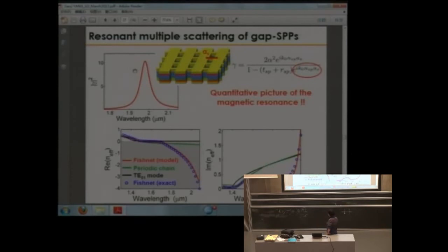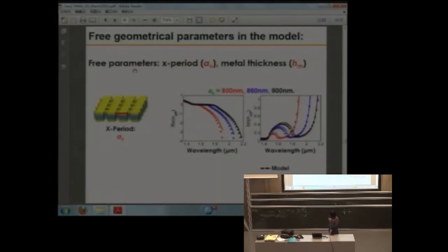So now the origin of the negative refractive index in fishnet can be understood: the strong resonance of the gap plasmon. And phenomenologically, this plasmon resonance can be understood as a very strong magnetic resonance, which can be further quantified by a negative magnetic permeability. As we have already made a very accurate model for the effective index of fishnet, we also try to use this model to design fishnet further.